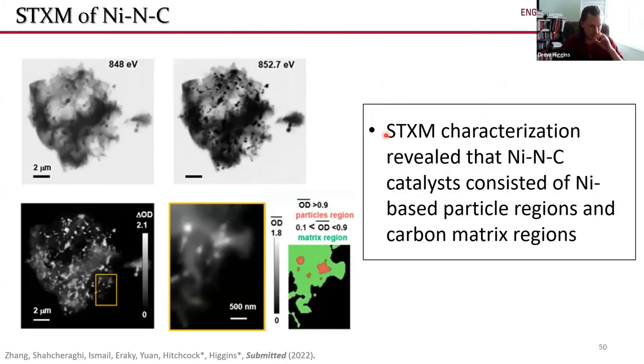And so I'm not going to dive too much into the details here, but essentially what we found is that these catalysts, as I showed a little bit before, consist of two particularly distinct regions. One of those regions is what we call particles, so you can see these very dark spots that are likely nickel-based particles. So in this case, it could be metallic nickel, nickel sulfide, or nickel oxide. And then these carbon matrix regions that just kind of look like graphitic carbon.